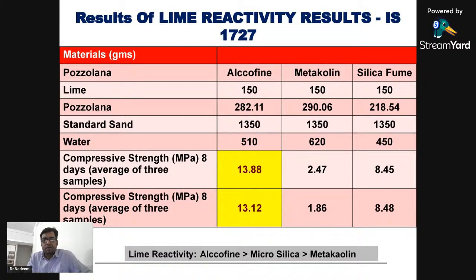So one side is Alcofine, giving a compressive strength of say around 13.8 or 14 MPa. Metakaolin is giving 2.47. Silica fume is giving 8.5, which indicates the lime reactivity, or reactivity of a pozzolanic material with lime. So here reactivity is.